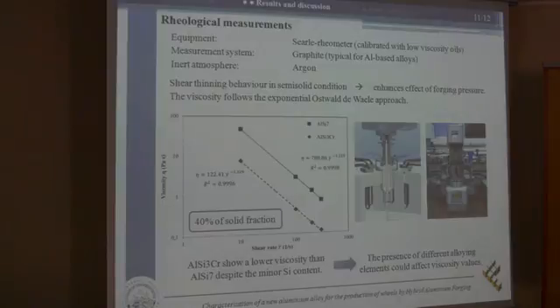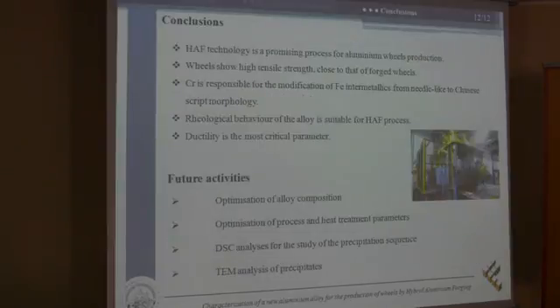Finally, we also performed rheological measurements, always in semi-solid condition, with 40% of solid fraction. We detected a shear thinning behavior in semi-solid condition, that is, the viscosity decreases as the shear rate increases, and this is positive because it can enhance the effect of the forging pressure during the process.